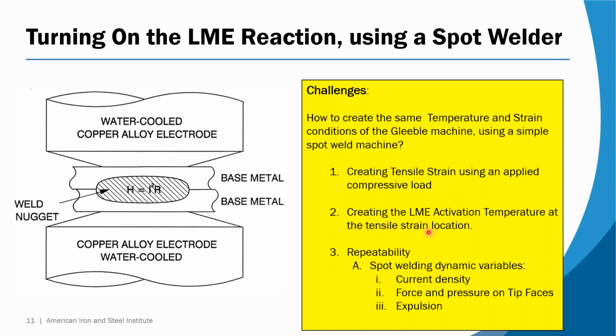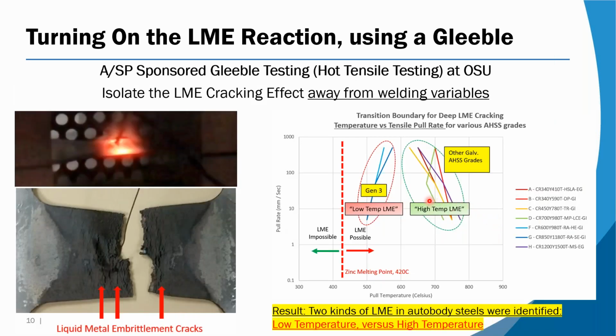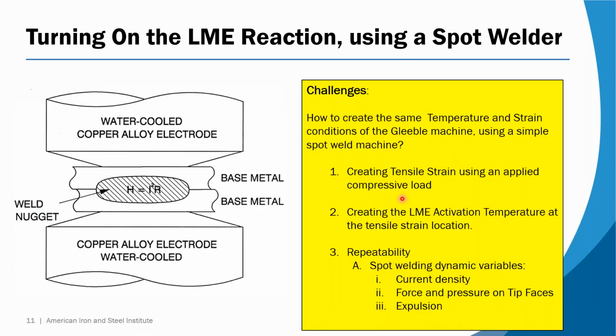Secondly, how are we going to get to the same activation temperature that we observed in the Gleeble test? Okay, activation temperature, let's say it's the Gen 3 here, strain rate of 100 millimeters per second, and we're trying to get to 530 degrees, something like that. So how do we do that with a spot welder? How do we control the temperature of the heat affected zone?